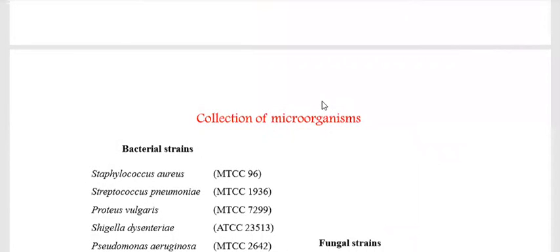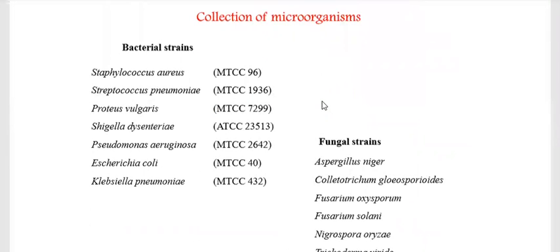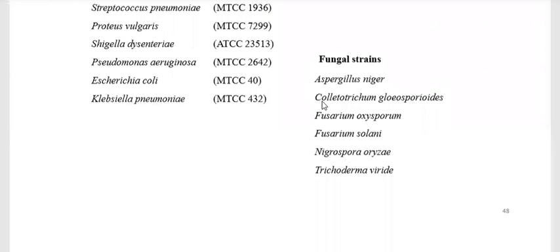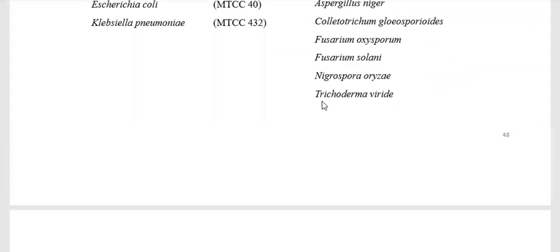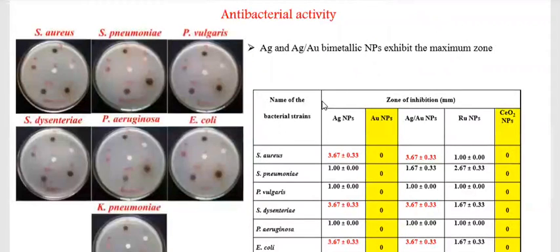Staphylococcus aureus, Streptococcus pneumoniae, and so on. So 2 gram-positive and 5 gram-negative bacterial and 6 fungal strains were used for the antibacterial and antifungal activity. The bimetallic nanoparticles show better antibacterial activity, followed by the silver nanoparticle and ruthenium nanoparticle. By contrast, the gold nanoparticle and cerium oxide nanoparticle didn't show any activity, due to their biocompatibility.